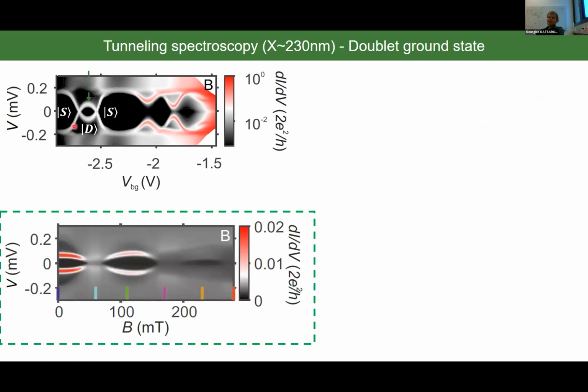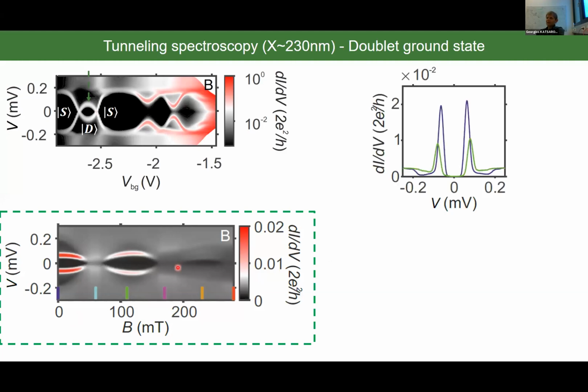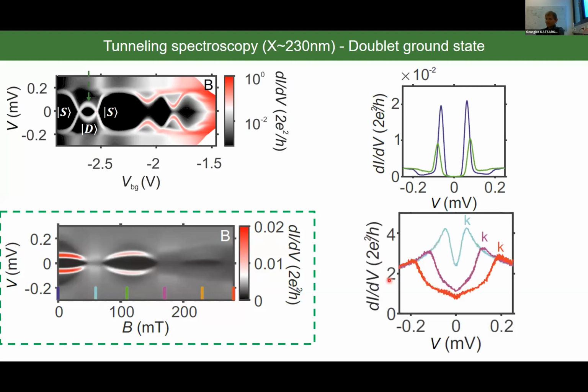So let's fix now our gate voltage to the green position, and let's measure again the differential conductance versus bias and magnetic field. And we can observe now how the Andreev bound states evolve. I already showed you that if you take the line scan here, you will see that the Andreev bound states are lying at higher energy compared to zero field. And if now you take line scans in the destructive regime, you will see this split peak, which is nothing else than the Kondo split peak.